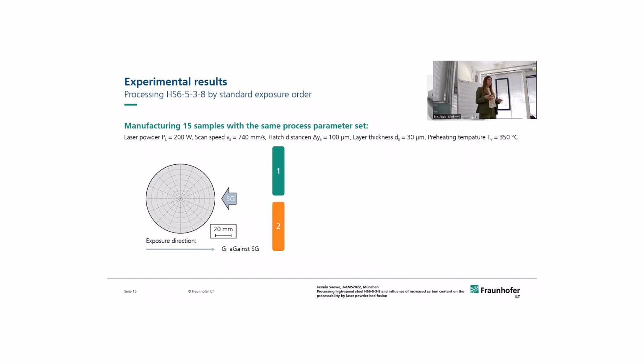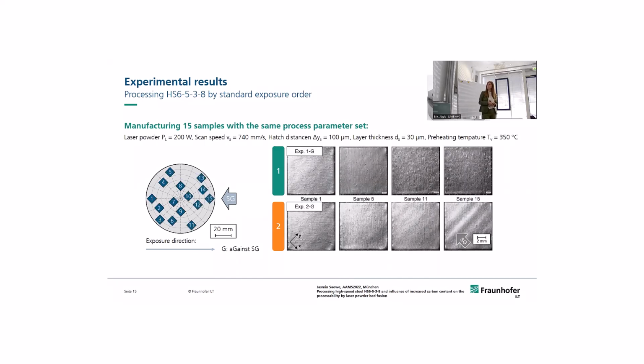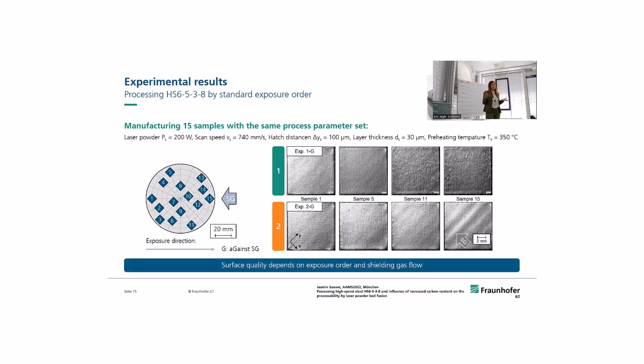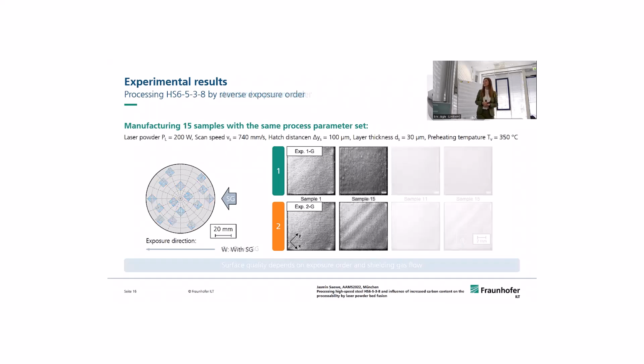We just used this one process parameter over the whole platform and printed 15 samples. And looking at the setup 1 and 2, by exposing those 15 samples, looking on the top of those parts, you can already see that there is an influence over those exposure order, and the surface is a little bit not as shiny as in the beginning for the setup 1. And for setup 2, you can even see that we might have a lot of energy input at the last cube still, that it has such waves along the surface. So it seems that the surface quality depends on those two shielding gas flow setups.